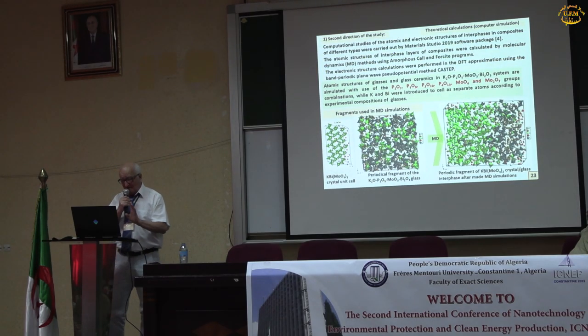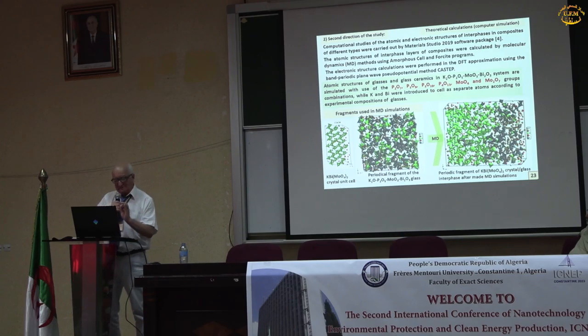Some results. We use so-called molecular dynamics methods, where we first regard the crystal structure separately. Then we combine various molecular groups, shown in red, and combine the composition of the glass under experimental study. You see it in the middle. Then we use this program for molecular dynamics calculations, and we obtain the composition and structure of the composite materials. We see that the molecules and fragments of crystals and fragments of the glass incorporate each other.